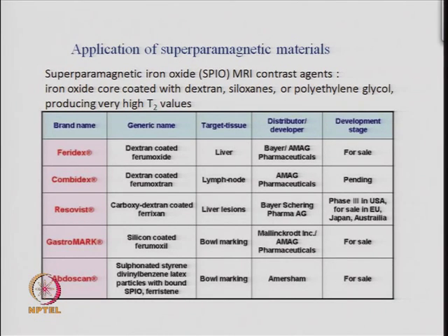They are given into the body, it is transmitted, normally coated with dextran or siloxanes or polyethylene glycol. It is coated with these materials. Inside is the iron oxide, which is of a very small size, because it has to be super paramagnetic. So, the idea is you do not want ferromagnetic iron oxide, you want super paramagnetic iron oxide. That means, you want nano sized iron oxide, and these nano sized iron oxide, when coated with some of these, are sold in the market under different commercial names.